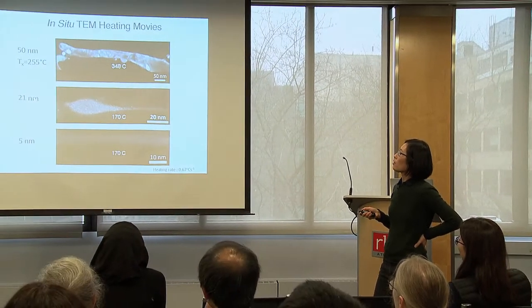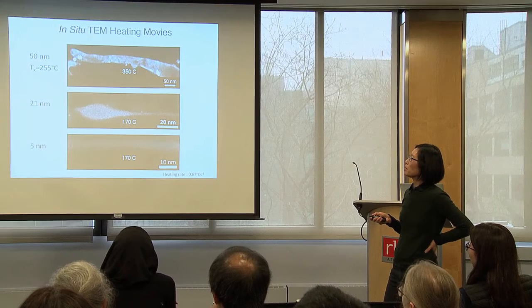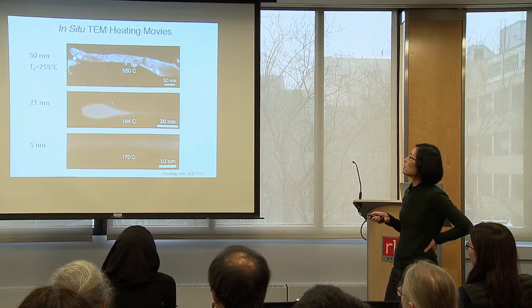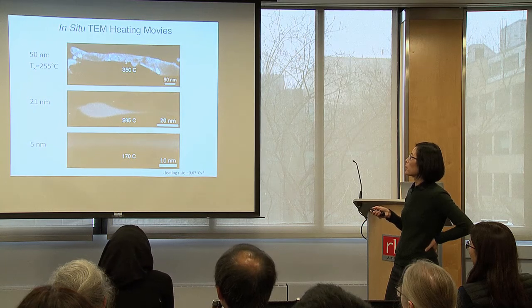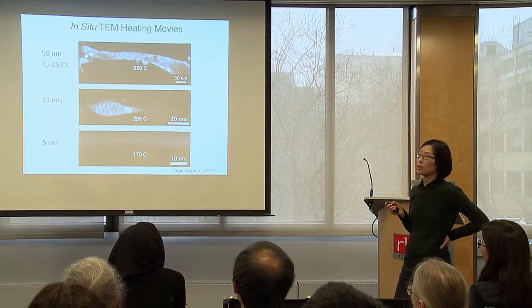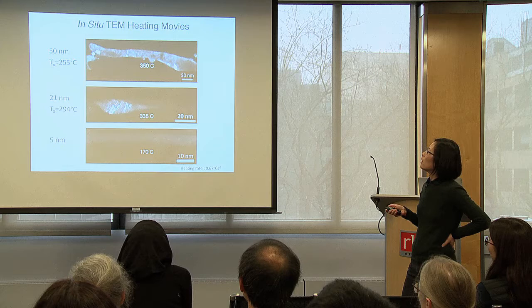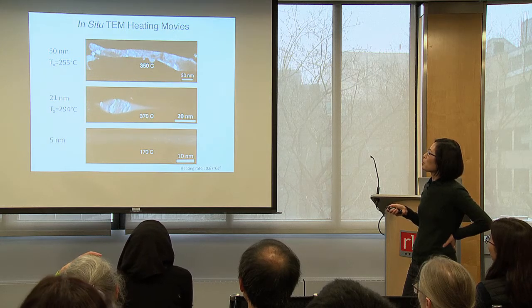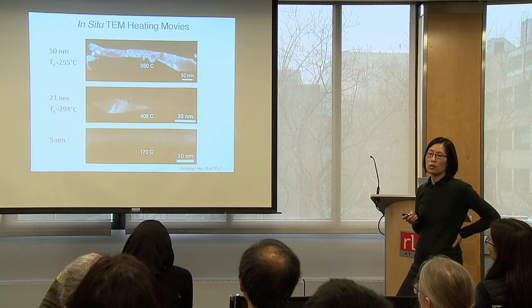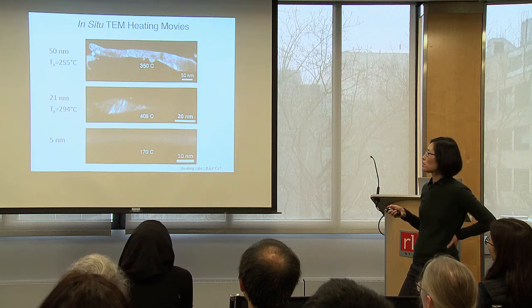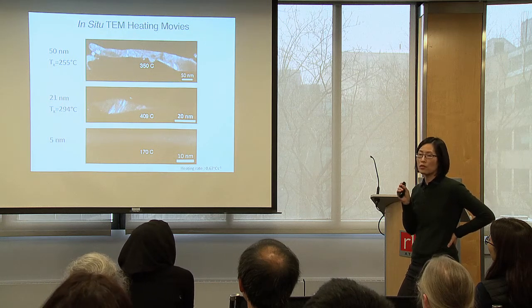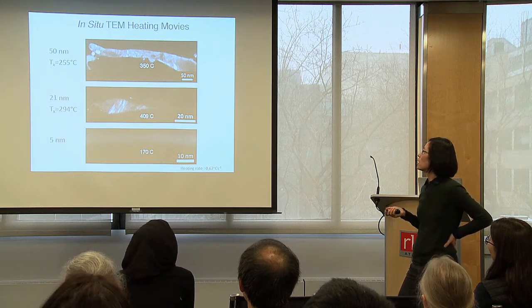Here is now a rod that's 20 nanometers. This part is 20 nanometers. Actually, it tapers down, and this necking, this part is actually below 5 nanometers in diameter. So this 20 nanometer region crystallizes around 294 degrees Celsius. So the onset of crystallization temperature is different.